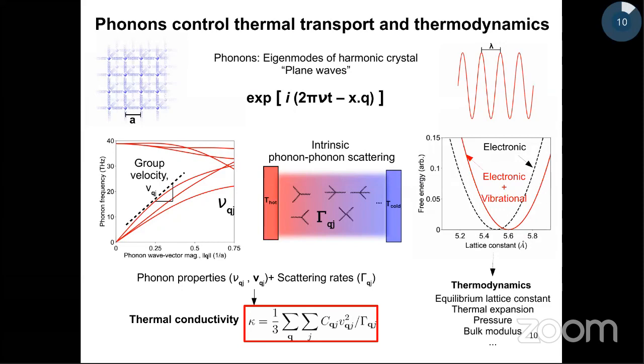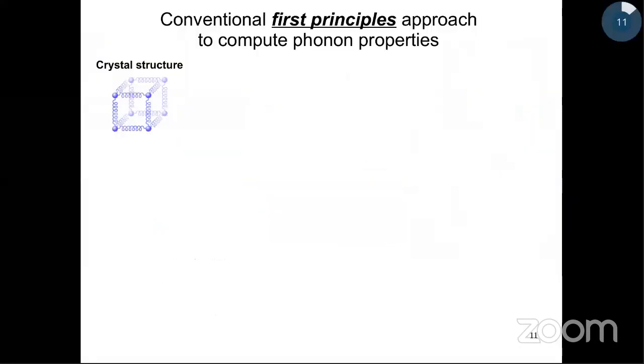So as I mentioned earlier, phonons also control thermodynamics because they contribute to the vibrational component of the free energy. So if you know the free energy of a crystal, you can essentially calculate various thermodynamic quantities such as equilibrium lattice constant, thermal expansion, pressure, bulk modulus, etc. at finite temperature. So recent advances over the past 2 decades in first principles computational technique have enabled us to very accurately calculate these microscopic phonon properties and therefore the macroscopic thermal and thermodynamic quantities. So this first principles approach is predictive and it's free of any adjustable parameters.